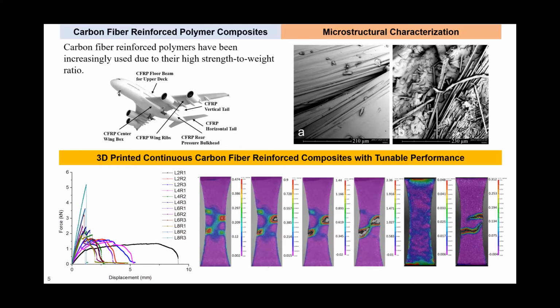So here you can see we fabricated different amounts of continuous fiber at different layers. In this case, you can see this legend indicates the number of fiber rings in each layer, and also the number of fiber rings at different layers. So you can see we also performed a mechanical test, in this case a tensile test, and we can tailor the tensile behavior by varying the amount of continuous fiber at each layer.